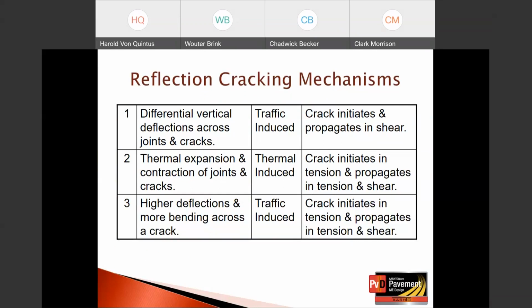The second mechanism is thermal expansion and contraction of the joints and cracks in the asphalt and/or rigid pavements. Obviously, that is thermal induced, and the crack initiates in tension, but propagates in tension and shear over time. The third mechanism is bending related, and that's where we get higher deflections in the overlay directly above the cracks in the existing pavement. Obviously, this is traffic induced, and the crack initiates in tension or flexure, and then propagates in tension and shear itself.